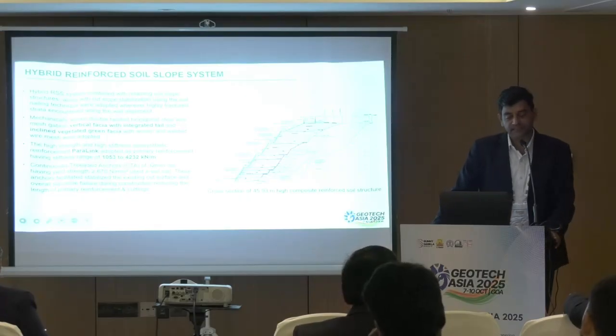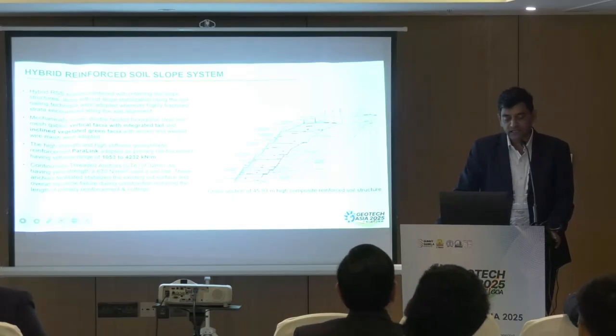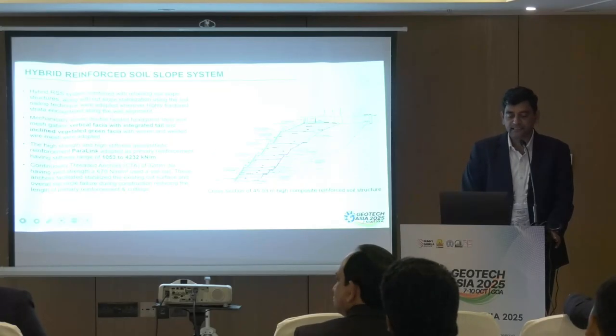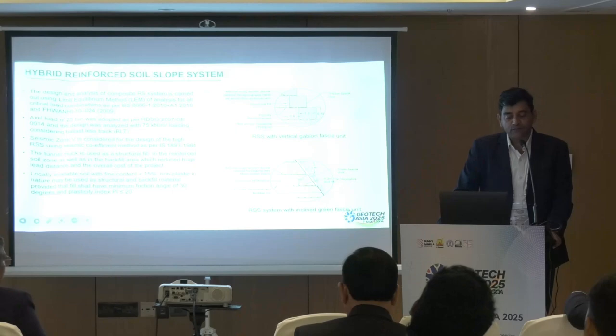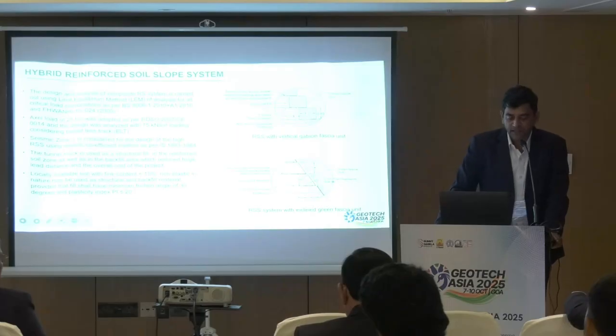So here we have used the high strength geogrid Paralink with a stiffness range of 1053 to 4232 kilonewton per meter. The anchors used were continuously threaded anchors, yield strength more than say 670. These anchors basically stabilized not only the slope, but during excavation the stability of the slope had to be ensured because it's a 50-meter tall structure we are building. The design followed the limit equilibrium approach as per BS 8006 and FHWA. As I said, the document for reinforced soil is not available, but we borrowed some portions from that.